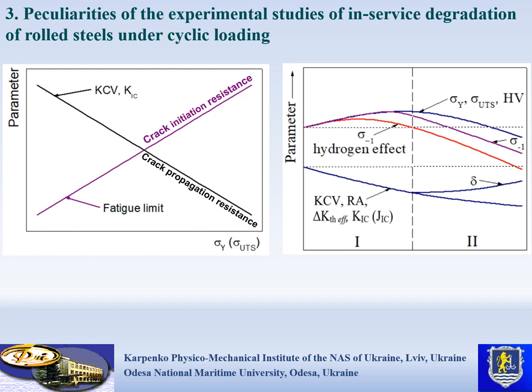It is principally important to understand the different law of strength and damage in the process of degradation. So, concerning operational degradation, a change of fatigue strength will repeat the unambiguous dependence on change of strength, detecting two stages of material degradation. Since cyclic loading is a stronger factor of damage than static loading, we should expect an early start of the stage of damage in comparison with static loading.